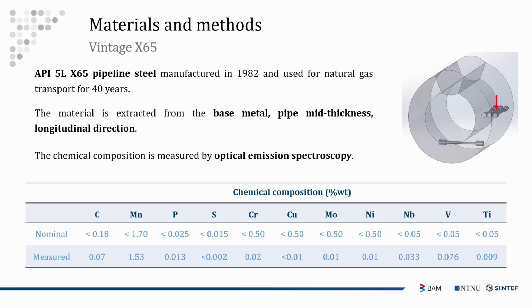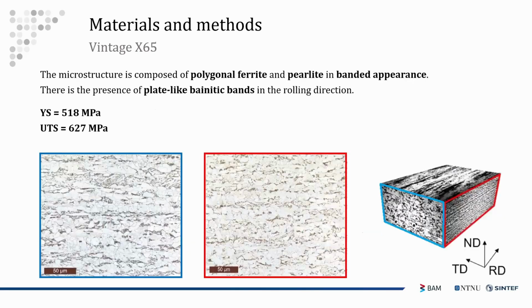The chemical composition was measured by optical emission spectroscopy and is coherent with the specification of the standard API 5L. The microstructure was also investigated, and it is composed of polygonal ferrite and pearlite in banded appearance, but there are also plate-like bainite bands in the direction of the rolling. We have also measured through strain rate tests the yield and ultimate tensile strength. And basically, we figured out that this banded microstructure could result in a highly anisotropic mechanical behavior of the specimen tested both in air or argon and in hydrogen. But we will talk about it later.